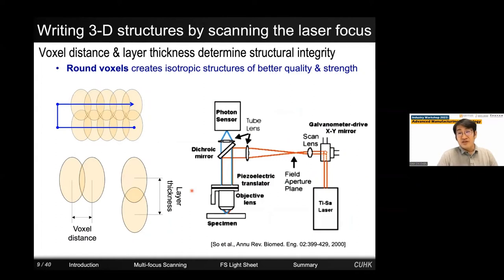So this is what's been done in the past. People pair the femtosecond laser with a pair of scanning mirrors. As a result, by raster scanning the laser focus, voxels can be created in a line by line, layer by layer fashion. So when one layer is completed, the laser is moved to the second layer by a specimen stage or piezoelectric objective scanner to complete the 3D fabrication process. And this is very slow.